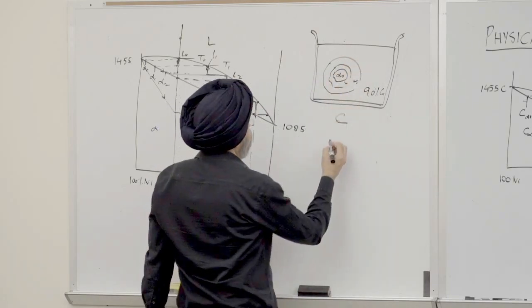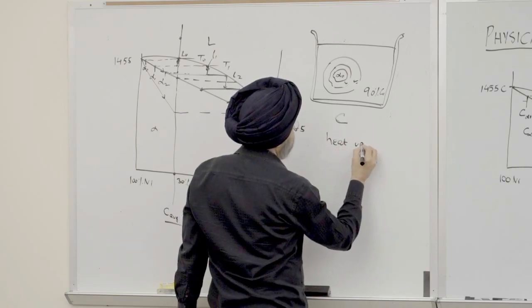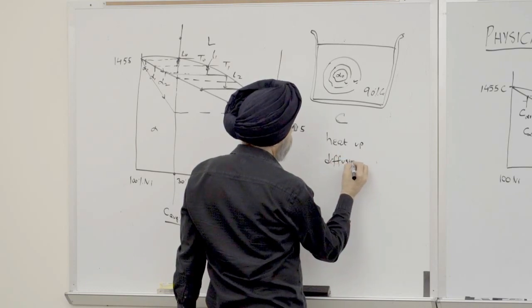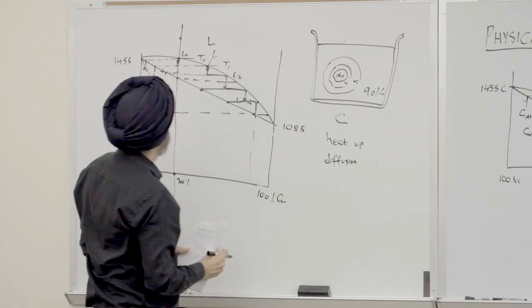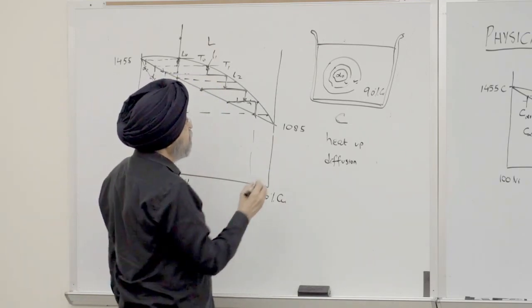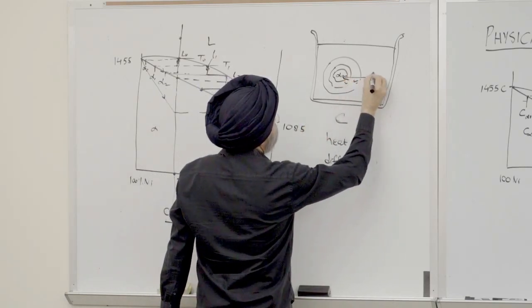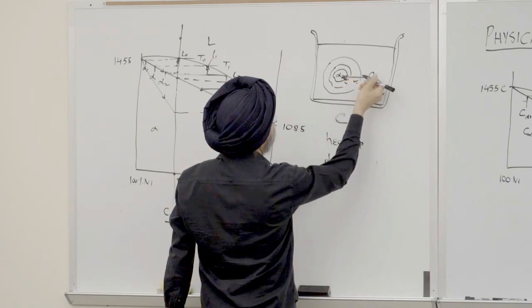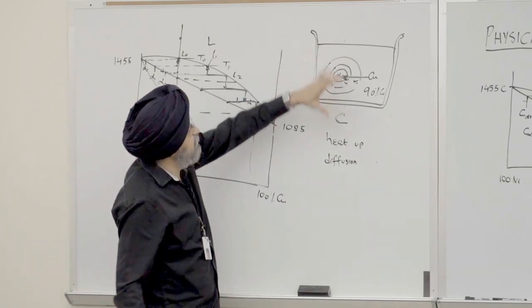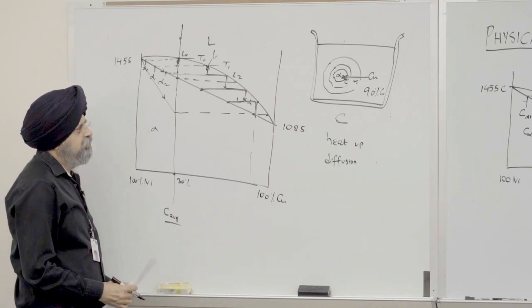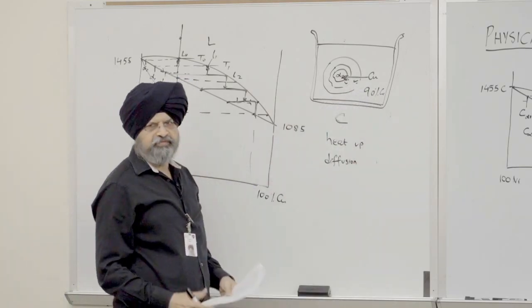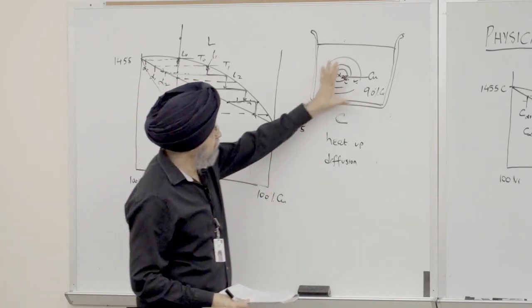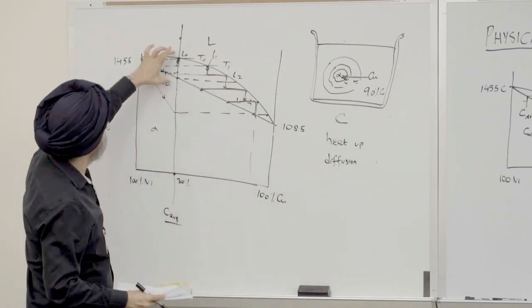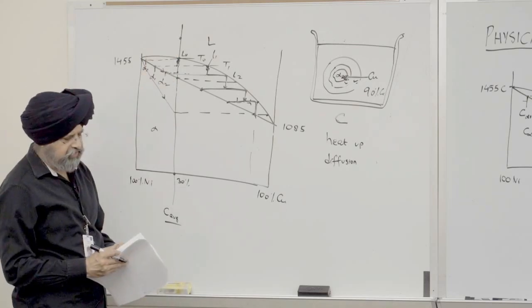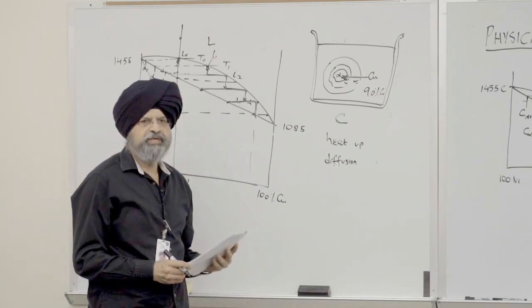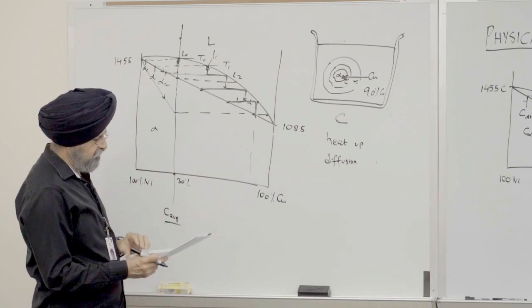So how do you reach equilibrium? You heat. You heat this up, and the diffusion of the atoms will bring this into equilibrium. So to achieve equilibrium conditions, the copper atoms have to keep diffusing into the solidified material. So you need time and temperature to cause this diffusion to happen, so that you can have a homogeneous material that follows the phase diagram. So you see, the basic message is phase diagrams are equilibrium diagrams. They are only good for very slow cooling.